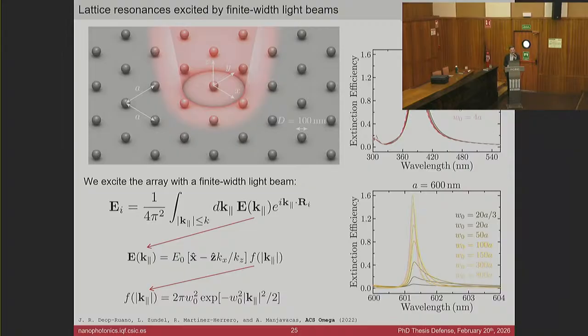Note that here, although these resonances look like they have the same width, we have a really different scale. This is a much narrower resonance with a much larger quality factor. Because it's a more collective resonance, we need to illuminate more and more particles to sustain this resonance. This is why, in this case, the resonance is not highly collective, maybe just first neighbor interactions, and we converge to the results really fast, while here, this is not that simple.